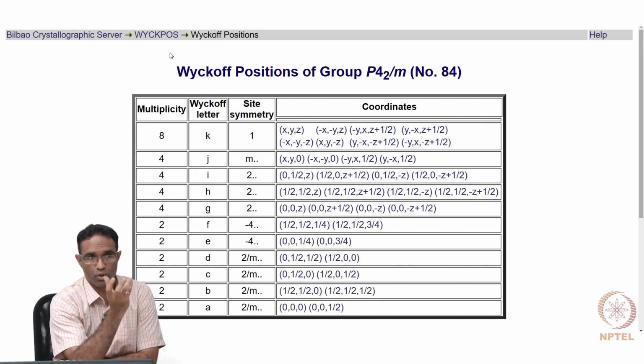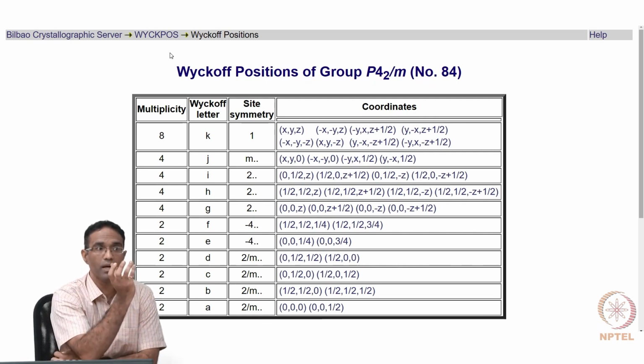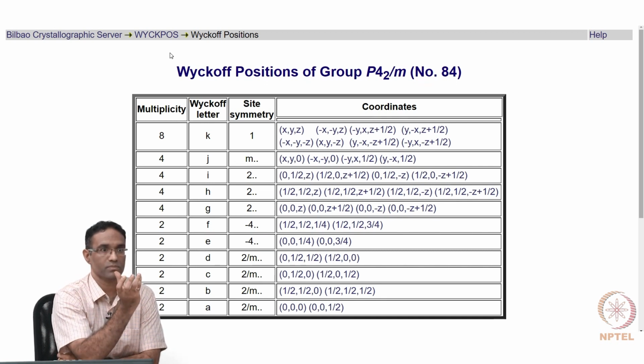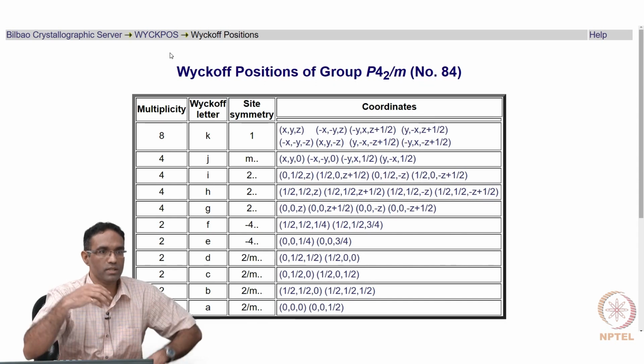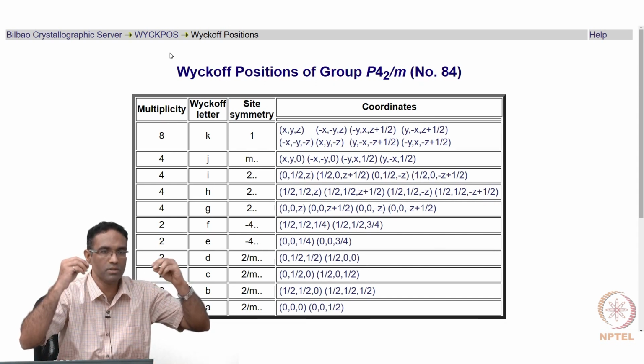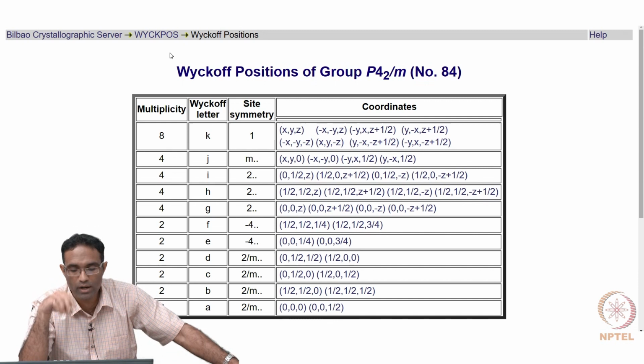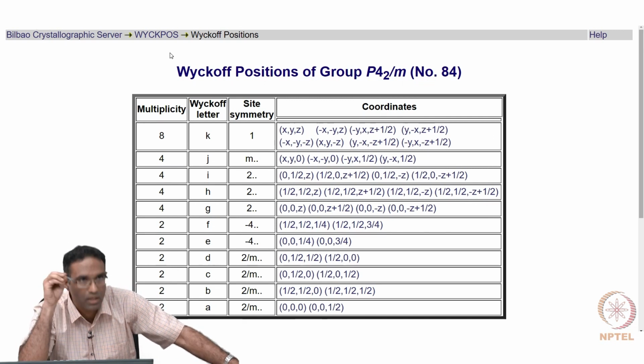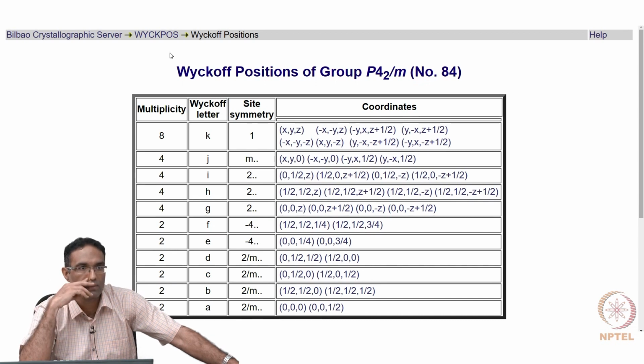It's not just a fourfold rotation, it's a screw axis. You are performing a fourfold rotation and moving it half the unit cell. And there is a mirror that's perpendicular to it. So the set of all these operations applied on one generic point xyz will generate these additional points. This is exactly what we did for P4, the simple case.